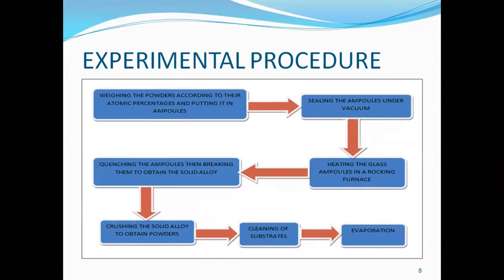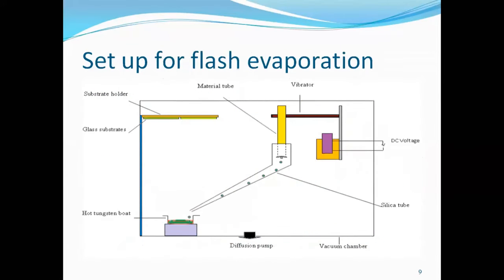Then the quenching was done. Quenching is done so that we end up getting an amorphous solid alloy. Then after the melt quenching, we did the crushing to obtain the powders, followed by cleaning the substrate and finally flash evaporation. Now these are simple setup for flash evaporation. Of course, evaporation is well known to us. It is heating and evaporating. In this one, the only addition is the part of dispensing the powder. Here the powder is dispensed.